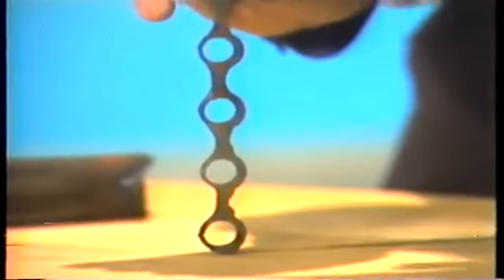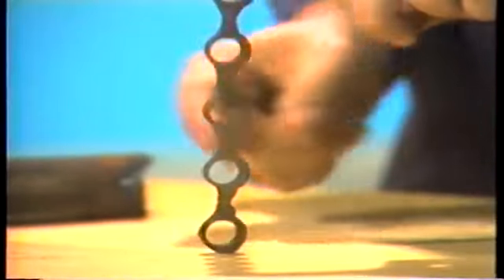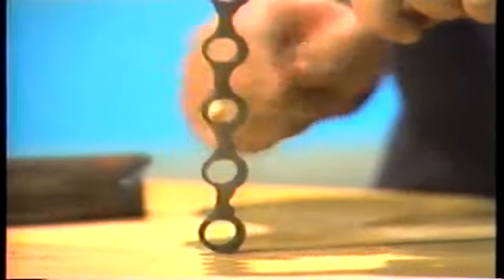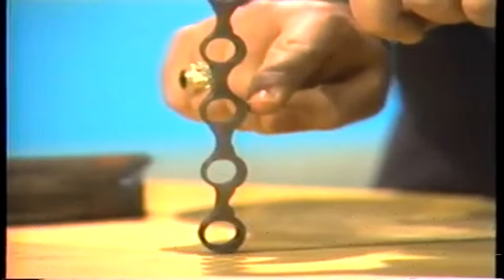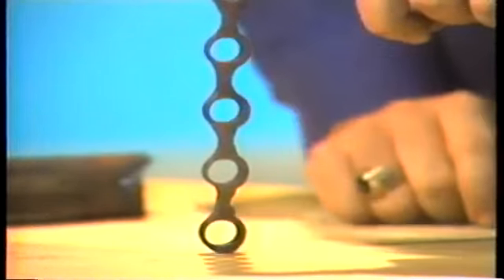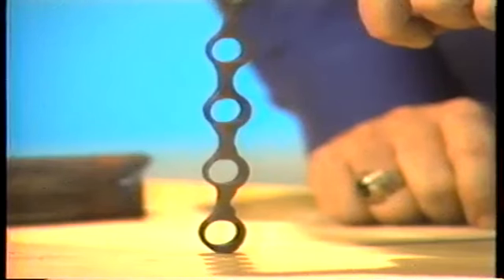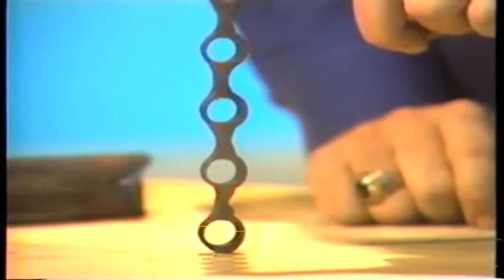Now, these tube sections were cut out of a water wall. You can see how much thinner this side is than this side. And when the thickness of a tube is reduced, the tube is weakened, and this can result in tube failure.